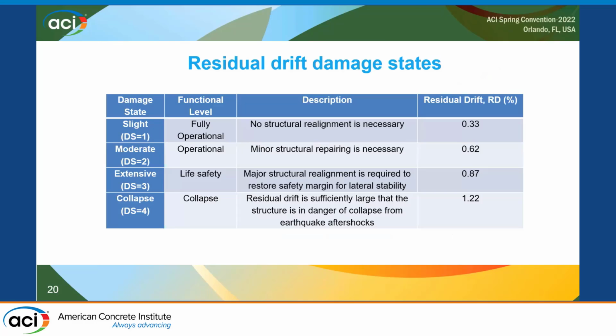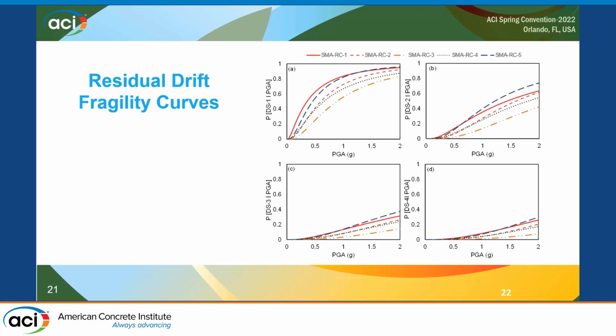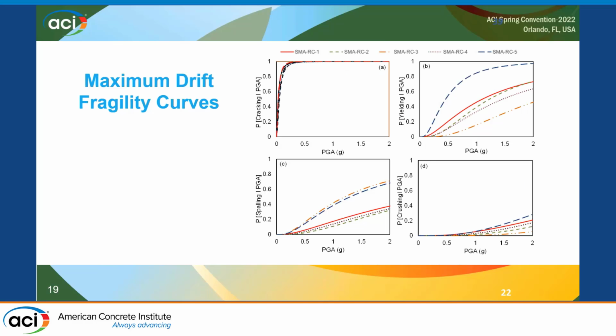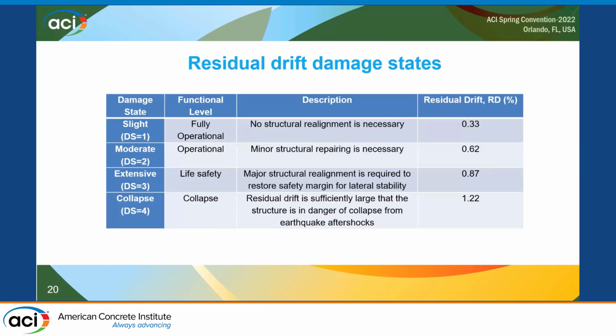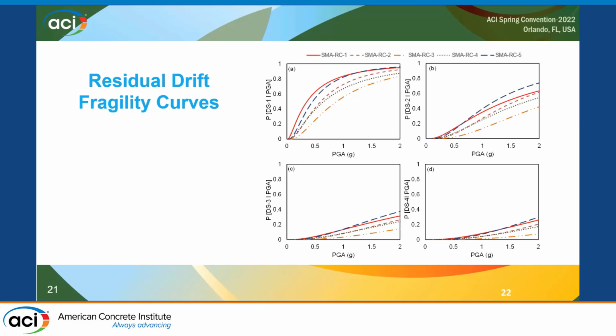And here I'm showing the residual drift limit of the damage states in the rightmost column. And these are the graphs of residual drift, but this graph has some dissimilarities with the maximum drift curve, as we can see from here. In this curve, for all the damage states, SMA-3 had the best performance. It showed the lowest probability of exceeding a certain damage state, as we can see from here. And this can be attributed to the higher recovery strain of the SMA-3 bar.